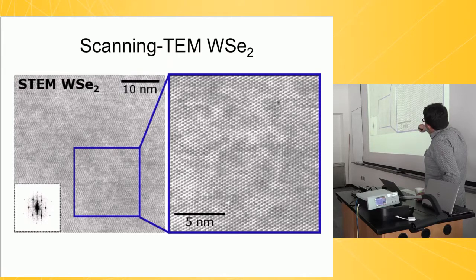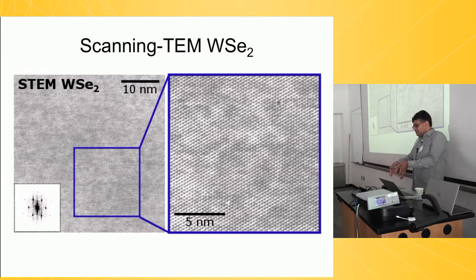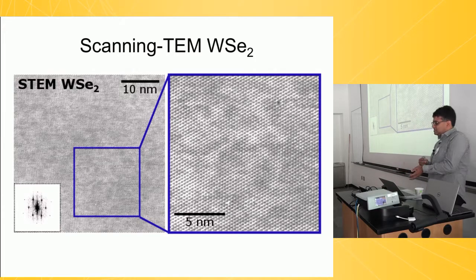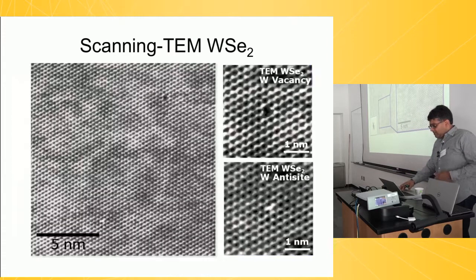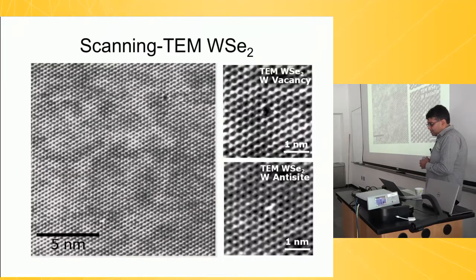So here is a big TEM image of one of these monolayers of WSe2, and there you see a metal vacancy. What we've done is characterize samples with STM. We've given them to our TEM collaborators. They study the same material and see how many metal vacancies there are. It matches pretty well with what we see in the STM, so we're pretty happy about that.